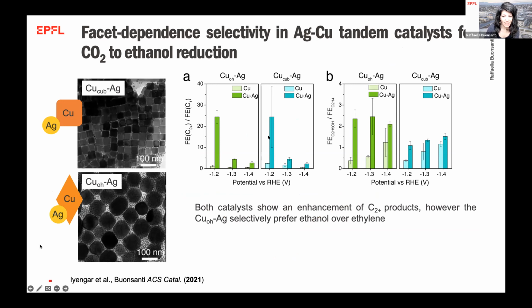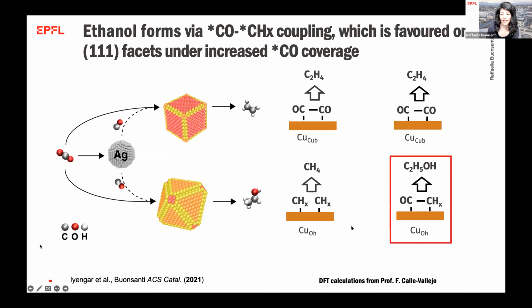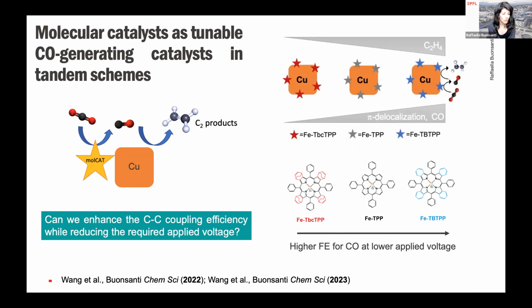is that in both cases, there is an enhancement of the Faradaic efficiency for ethylene, which is expected based on the tandem catalysis. However, it was a surprising result to find that actually the copper octahedra selectively prefer ethanol over ethylene, which provided then insight into the mechanism behind ethanol formation, which I won't go into the details of. Because I also want to refer to the importance of the interface,